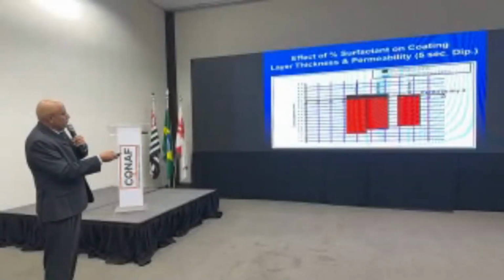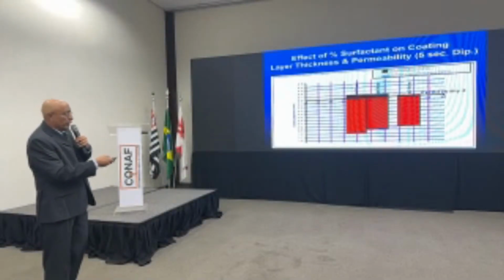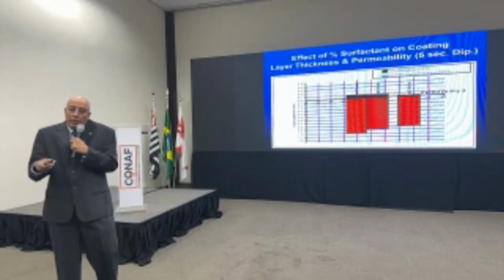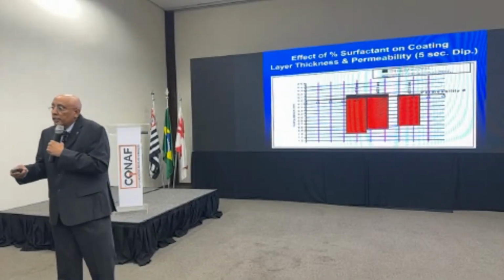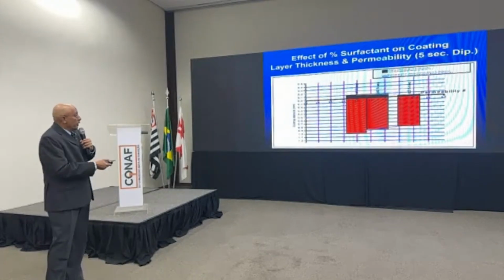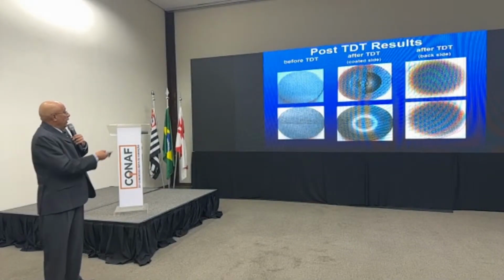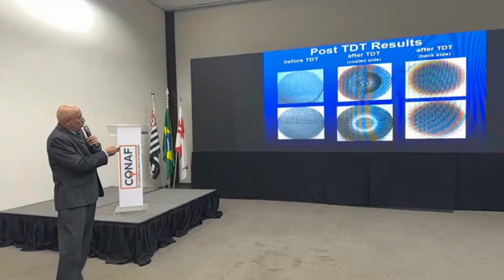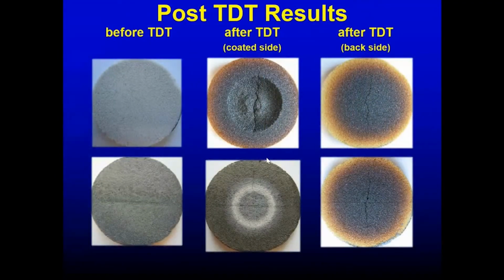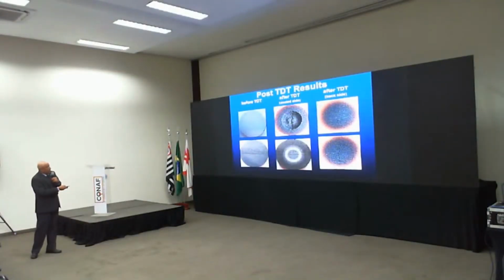So permeability increases with less coating. We literally can use permeability data to tell us how much coating is there. Okay? It is a direct relationship. We have measured that. So here are specimen cookies, uncoated. These are naked cookies after thermal distortion, and the back side of the specimen. Again, the pyrolysis, this black layer, we can measure how much organics is left. And there is a significant amount. There is 40 to 60% of an organic binder there. It's not gone.